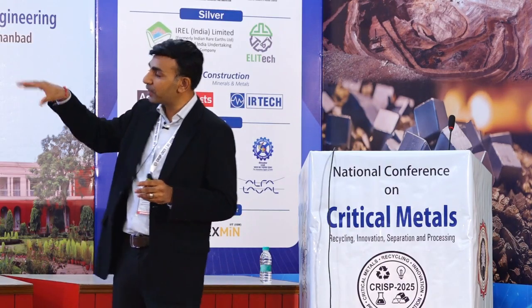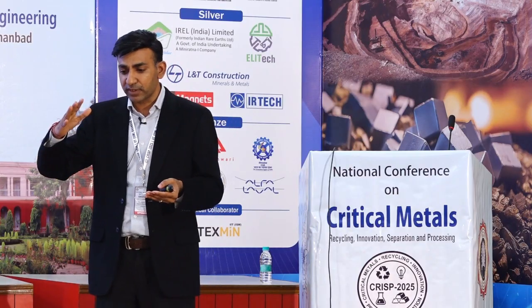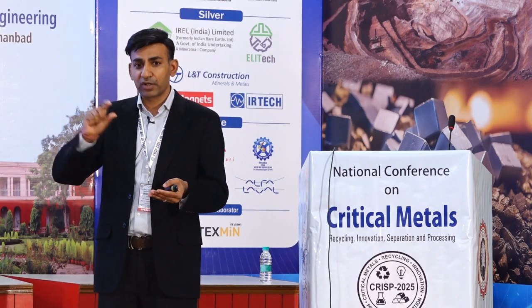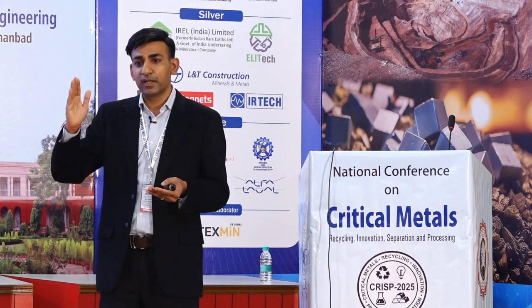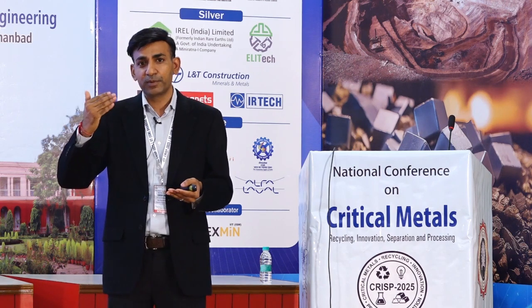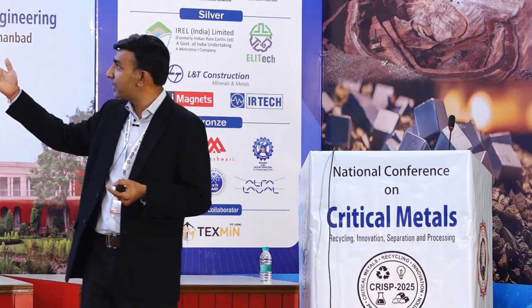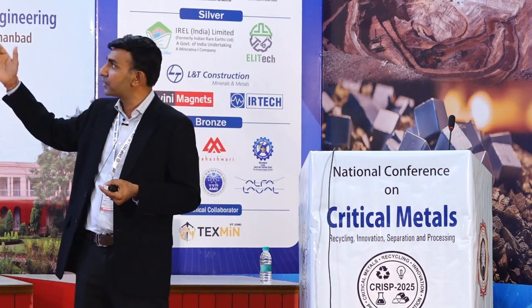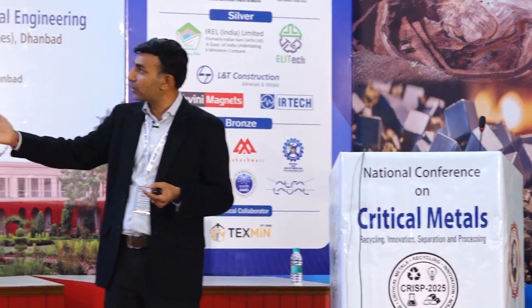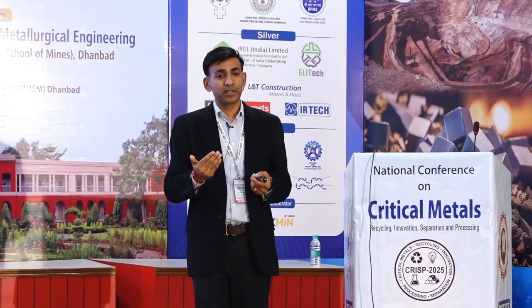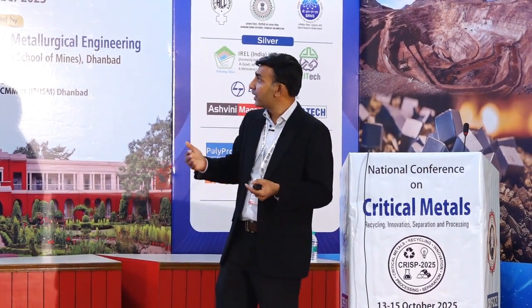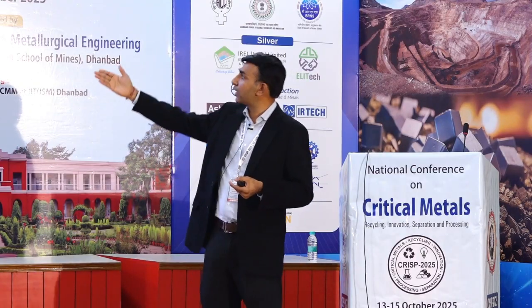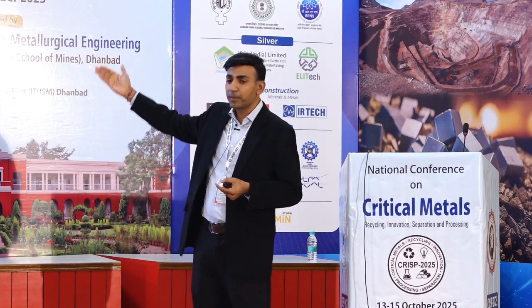Typically in a solvent extraction process there is an aqueous phase and an organic phase, and the metal goes towards the organic phase because of the solvent. So here you can see most of the manganese is going towards the DEHPA phase, and the cobalt and nickel are moving more towards the aqueous phase. Even now, people will say, I still have 4,000 ppm of cobalt and 2,000 ppm of nickel. It's perfectly normal. It's not because of the product. The product is doing the job.